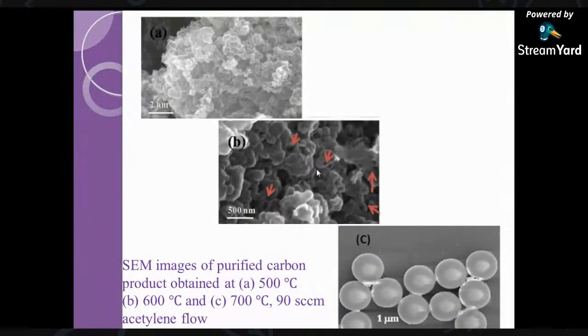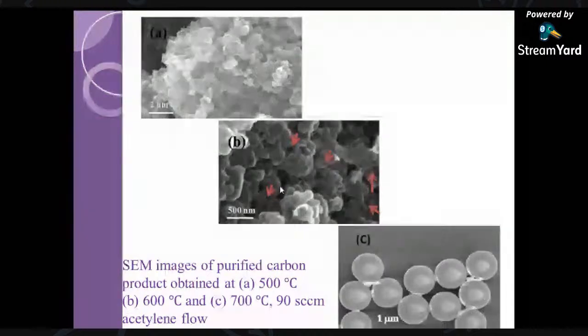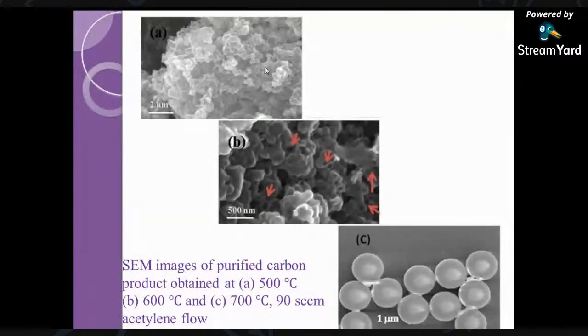So we have three different morphologies coming at three different temperatures. At 500 degrees centigrade, you can see a sheet-like or flake-like structure of carbon. Then at 600 degrees centigrade, you can see a change happening here, a transition from the sheet to a sphere. You can see some hollow structures, and an opening over here at 600 degrees centigrade. Then at 700 degrees centigrade, you see perfectly solid spheres without any hollow structures. So the variation of this structure is being studied at different temperatures.